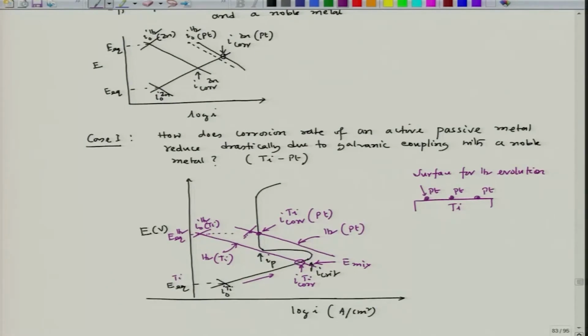And then I would definitely see that the corrosion rate when it was only titanium was at this location, and after having platinum on top of the titanium surface, corrosion rate becomes at this location, in the passive zone. So the corrosion rate decreases drastically because it is in the log scale.